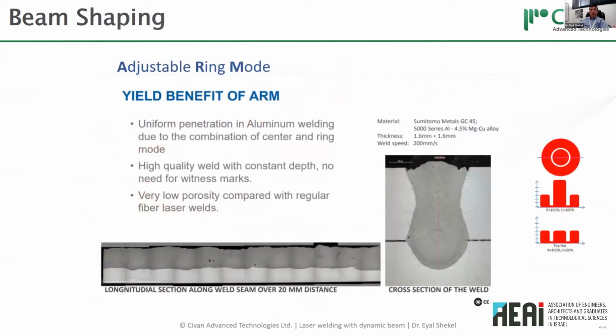The results are very nice. This is an example from Coherent, again just from their publications, to show the importance of beam shaping. This is an example where they use a donut with intensity in the middle, and this is welding of aluminum. You can see a very good weld, no cracks, very uniform penetration along the weld, and no porosity at all. This is achieved by a sophisticated beam shape, not just taking a Gaussian beam or a top hat, but rather a more sophisticated shape.